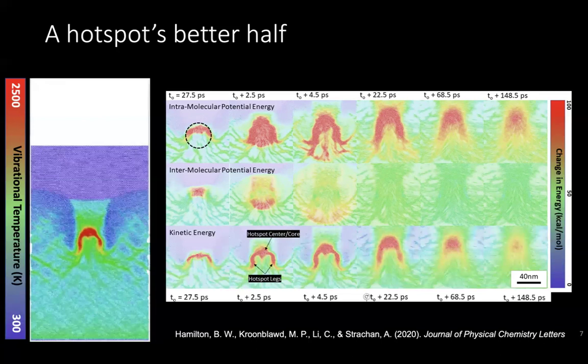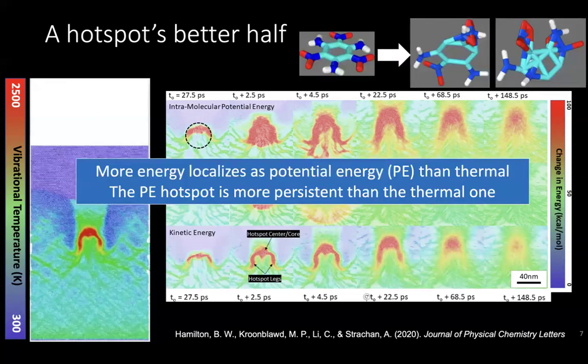What we found is that the potential energy is more intense. These are the same units of energy. It's more intense and it's more permanent. It doesn't dissipate nearly as fast as temperature. You can diffuse away this internal strain in the molecules. So if you zoom in, what happens is these molecules, this is a molecular crystal, they like to be flat. At the hotspot, they're all twisted out of shape. They're literally bent out of shape, okay? And so that was the first hint that the reactivity may have to do not with temperature, but with the potential energy, okay, with the distortions of the molecules.